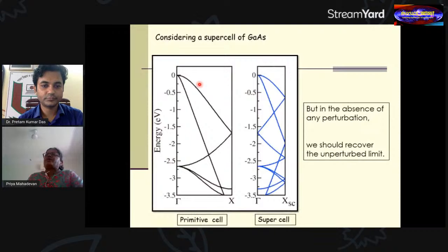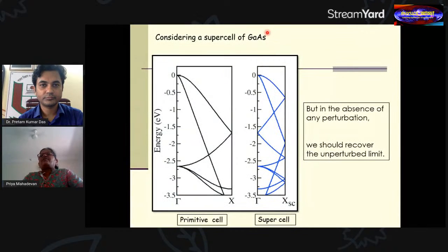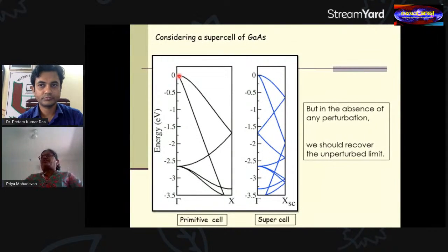What I mean is that if I took a cell, in this case gallium arsenide, made some repeat units and constructed a supercell, and plotted the band dispersions along the supercell reciprocal lattice vectors, I see many more bands emerging. I also see that if I talk about the width of the band, this band is very wide, whereas over here the topmost band has a narrow width. And if I made it 100 times larger, I would actually get a band which has no width at all.